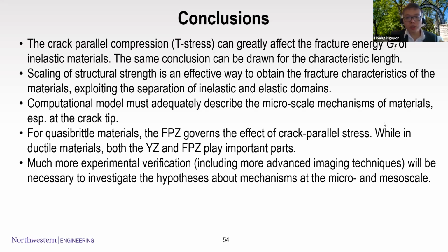And for quasibrittle material, the FPZ is the one that mainly interacts with the sigma XX, and in the ductile material, the yielding zone is the one that plays an important role. And at lower scale, the FPZ will start to manifest itself. And as I mentioned during the talk, much more experimental verification is necessary, not only for other materials but also to image what we have hypothesized as mechanism within the micro and meso scale happening at the crack tip.